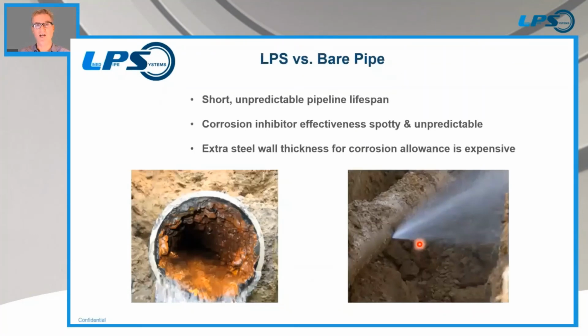Bare pipe without any internal lining is actually one of the choices that have been made throughout the years, and I think primarily because there really has not been a good solution for welded joints with internally lined pipe. So you really have a short, unpredictable lifespan. They will generally build extra wall thickness in the steel to have a corrosion allowance. But the corrosion rate is often very unpredictable. It can corrode faster in one location than another. And it's generally frowned upon. A couple pipelines are being built right now that we're aware of, where many engineers are really questioning why they went without an internal lining.